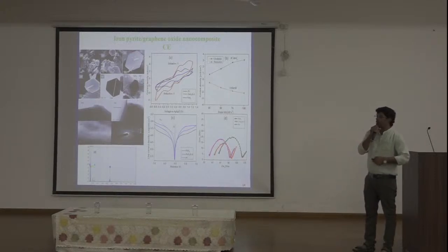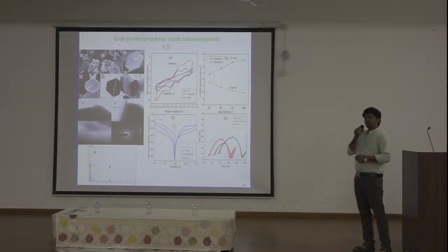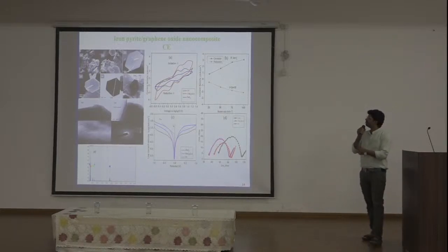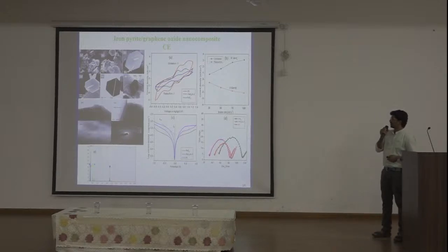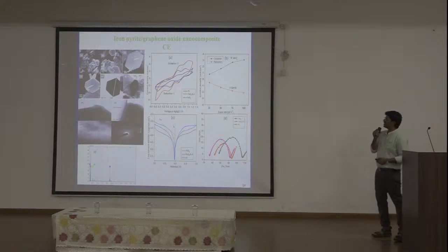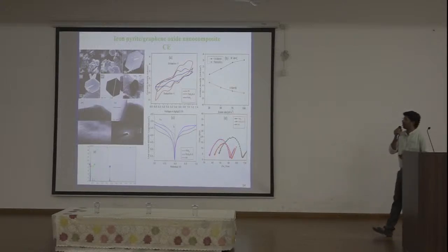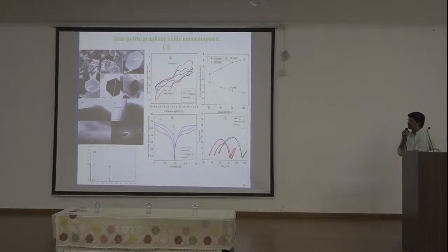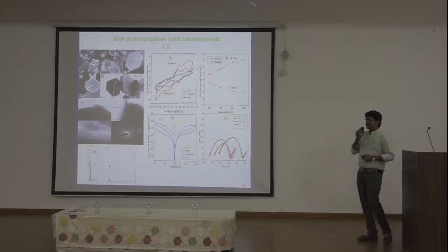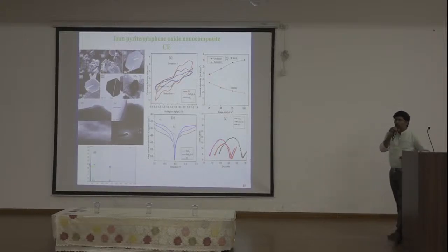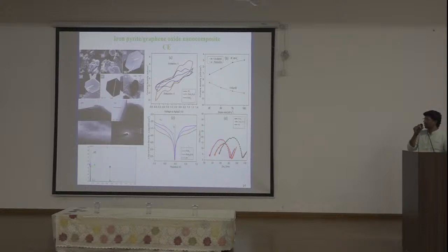It is a good platform for the growth of FeS2 nanoparticles. So the particle structure is also changing while increasing the concentration of RGO, because of more growth of FeS2 on the graphene oxide sheet. And also we can see in TEM analysis that the iron pyrite hexagonal-like structure is growing on the reduced graphene oxide sheet.